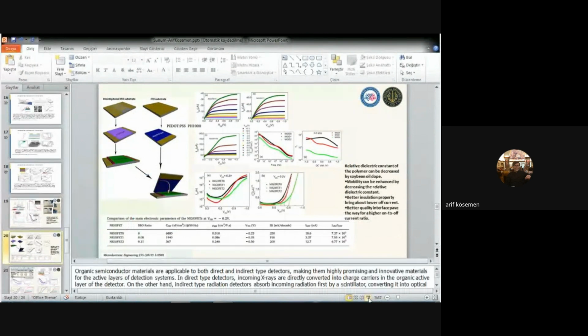And this is our other study. We used the gel structure again, with this sandwich structure to get low operation voltage, but we changed the polymers. Instead of polymethyl methacrylate, we used polymethyl acrylate in combination with soybean oil, and the content of the soybean oil was changed, and we can get a high mobility and low operation voltage with this approach. The relative dielectric constant of the polymer can be decreased by soybean oil doping, and mobility can be enhanced by decreasing the relative dielectric constant, and better insulation property brings about lower off current. This is very important. A better quality interface paves the way for a high on-off current ratio. These are results from the study.